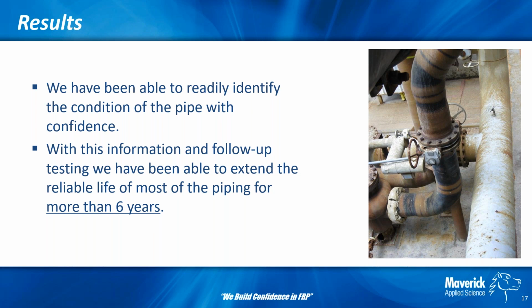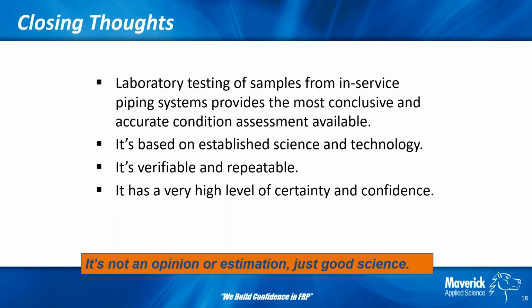And in this case, we've done this, I think, 3 times for this owner, about every 2 years. And that system, which they were concerned back in 2013 that they needed to replace, is largely still in service. Some of the worst areas they have chosen to change out, but I would say right now 3/4 of that system is still in service, so they feel really good about that. We were able to give them a very definitive report and the level of confidence that the operators can take to their management and tell them why they believe the system is still serviceable, and they have documentation to prove it. So that's largely what you're getting out of this process.